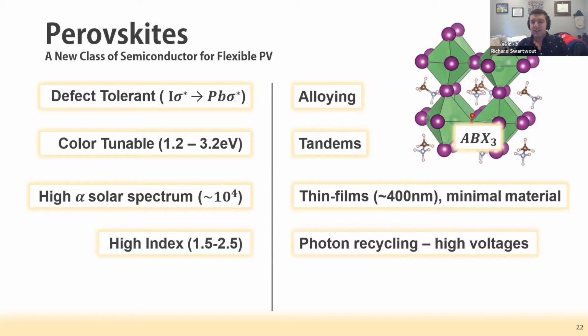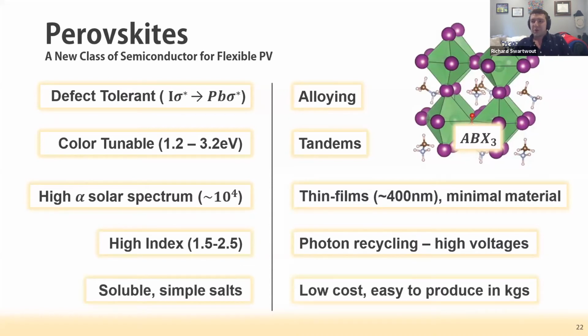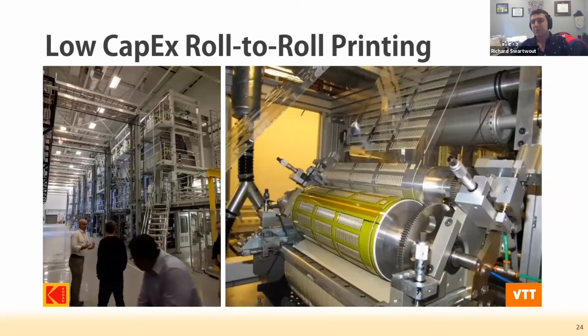They have a very high index. Again, I'm not going to talk about it today, but it means that we get photon recycling effects, thereby achieving high VOCs. And similar to gallium arsenide-based structures, we can get much, much closer to the theoretical efficiency limits for single junctions. The thing that's most important for the rest of the discussion today is that they are simple salts. They're really easy to produce at low cost in kilogram quantity, and they're soluble. That is the most important part, which really brings up the idea that we can use lower cost roll-to-roll printing methods to print these using relatively low capex processes.